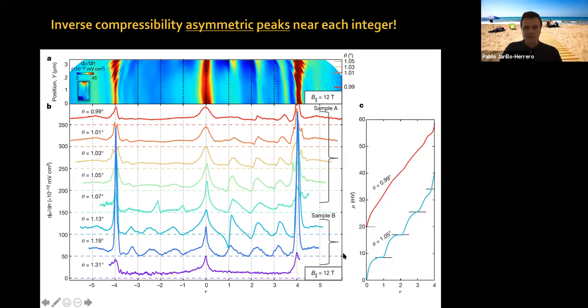If you integrate these curves again, you can see that the chemical potential versus filling factor for 0.99 degrees just follows this square root of n, pretty much from charge neutrality here. Then you have small undulations, but barely anything there. Whereas if you are deep into the magic angle range, you have these strong steps in your chemical potential versus density, versus filling factor. Strong steps which sort of repeat themselves are telling us that something is happening, okay?